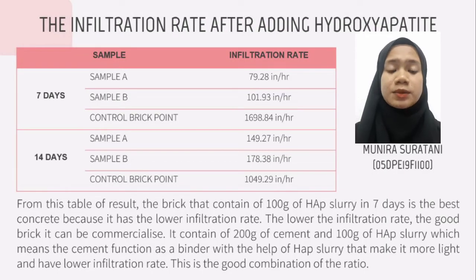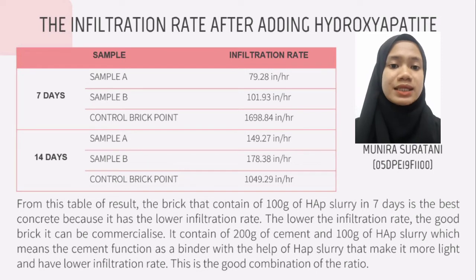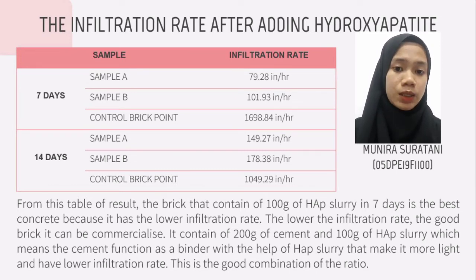From the result, the brick that contains 100 gram of HAP slurry in 7 days is the best concrete because it has the lower infiltration rate. The lower the infiltration rate, the better the brick can be to be commercialized. It contains 200 gram of cement and 100 gram of HAP slurry, which means the cement functions as a binder with the help of HAP slurry, making it lighter with a lower infiltration rate. This is the right composition of the ratio.